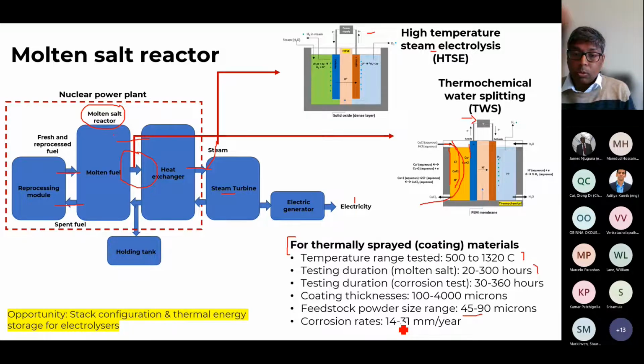That's quite high. If you take mild steel and put it in seawater, the average reported or acceptable corrosion rate for mild steel is about 100 micron per year. So if you compare that number with this 14 to 31 millimeter per year, that's quite a lot. So if you assume your molten salt is going through a channel made of some steel or superalloy, that will degrade the system. That's why you need a coating which can protect the structure so that you can use it for a long duration. And we also have a huge amount of thermal energy available, so it will be good to have a system where you can store that thermal energy to enhance the efficiency.